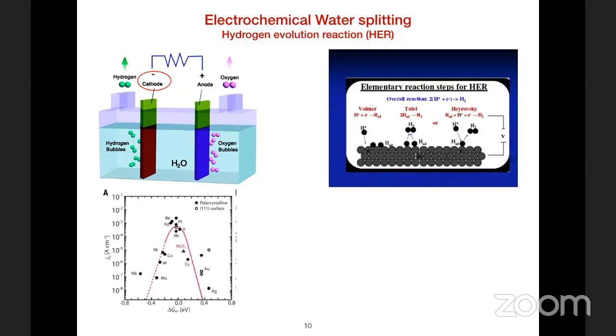So basically, one is looking for a simple descriptor, one quantity which will give you an indication of how good a catalyst it is going to be at the cathode. And experience shows that the simplest descriptor one can use is the hydrogen adsorption free energy on the surface. So delta E adsorption is just the adsorption energy that you can get out of your DFT calculations, for example. And then you add the zero point energy and the entropy difference terms, and you get the adsorption free energy.